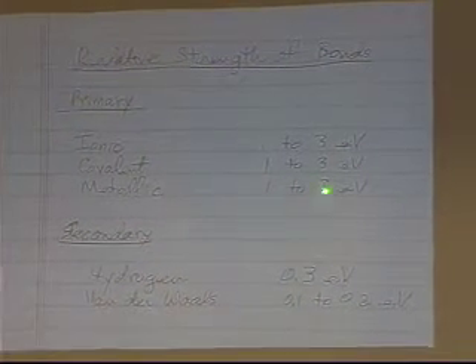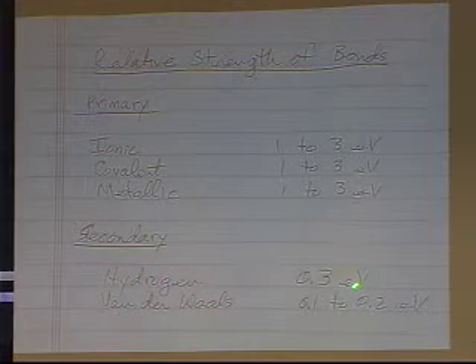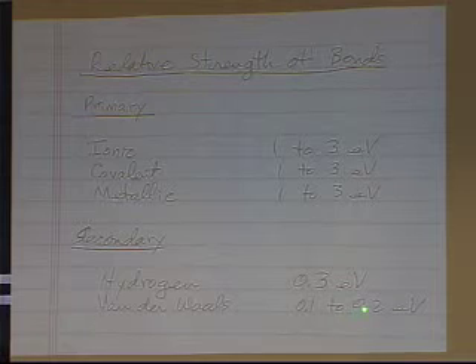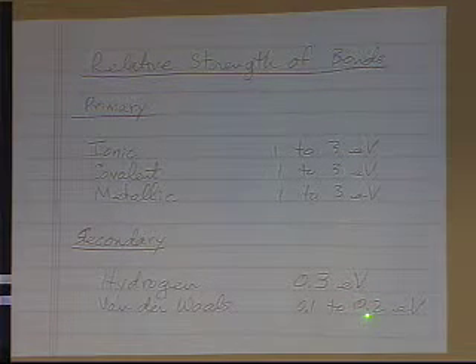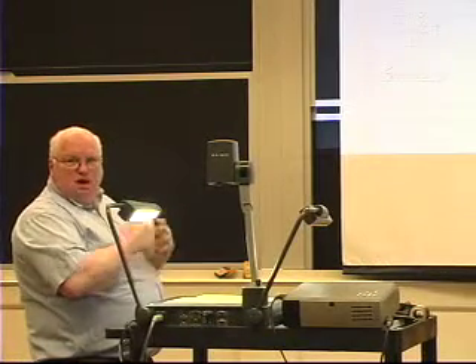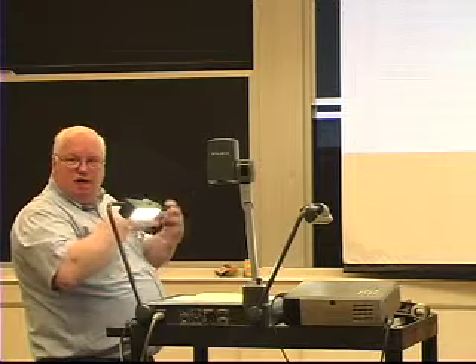If we look at the relative strength of bonds, ionic bonds are typically 1 to 3 electron volts per atom. Covalent and metallic are also in that same range. I'm going to break that down a little bit further for you. But the secondary bonds, hydrogen bonds, are about 10 times less, and van der Waals bonds are even lower. So why do polymers melt at low temperatures? Polymers melt at low temperatures because they're long chains of primary bonds, covalent bonds, along the carbon backbone. But in fact, there are van der Waals or hydrogen bonds between the spaghetti chains, right? It's like cooked spaghetti all mixed up.